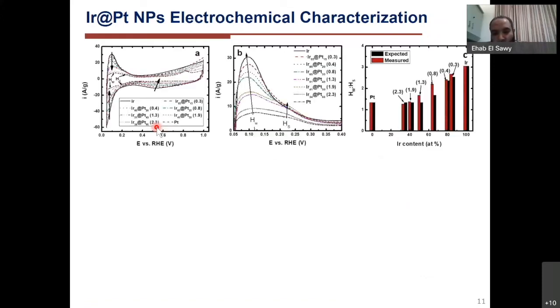Another challenge was to characterize the surface of these nanoparticles, because iridium and platinum are very close and it's very hard to see them through the TEM. So we needed a surface characteristic reaction that could distinguish between the presence of iridium or platinum on the surface. We first considered hydrogen underpotential deposition. In the case of iridium, the ratio between the weakly adsorbed hydrogen and strongly adsorbed hydrogen is about 3.9 to 1, while for platinum it's about 1.3 to 1.